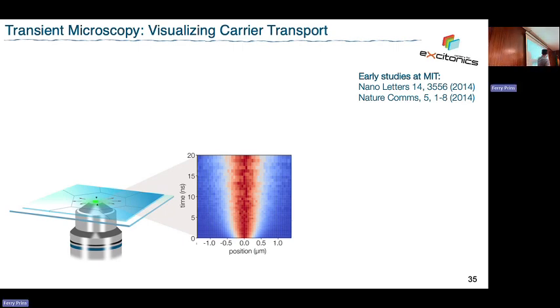What's important here is I've normalized out the decay of the excited state so that we focus purely on the broadening of the population. So now you can see that this initial population is broadening in time, and we can start analyzing that. You can see it clearly if you take time slices.